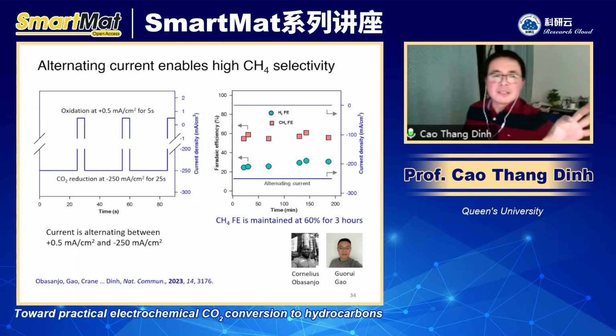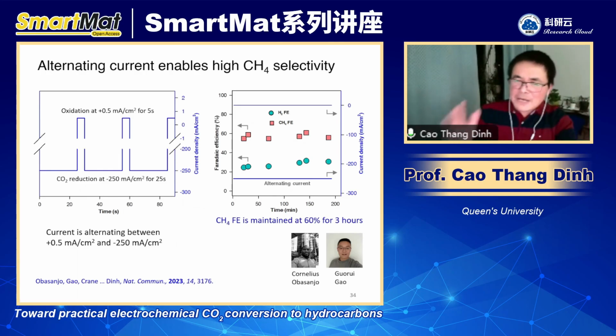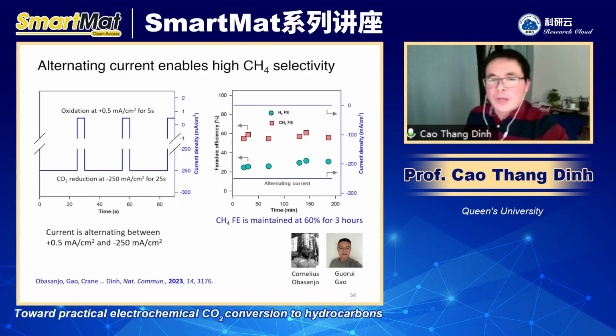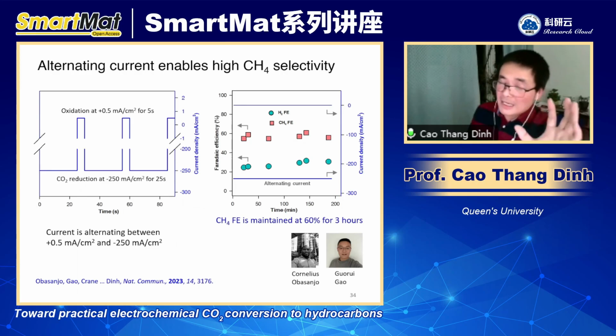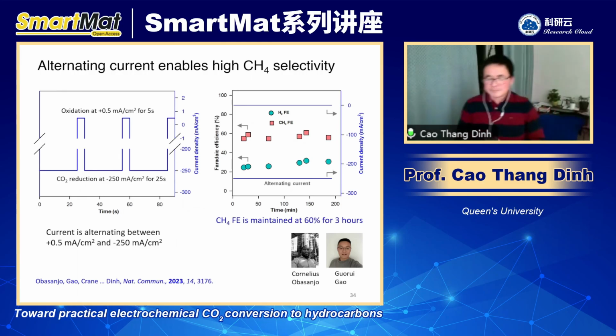We also use a very short time for the oxidation. It's a very small current going to the oxidation compared to the current going to the CO2 conversion. Now when we measure the selectivity, the methane selectivity is stable for about 3 hours, staying at about 60% selectivity, which is amazing.